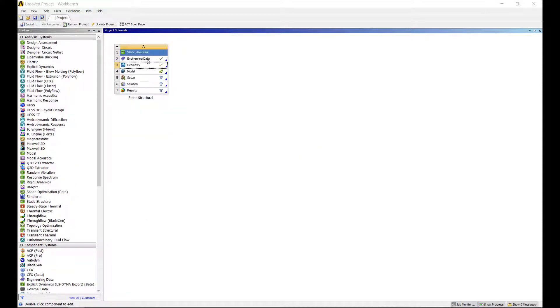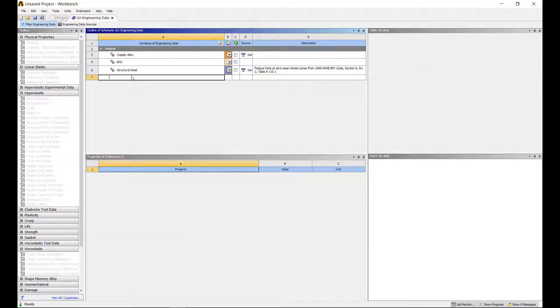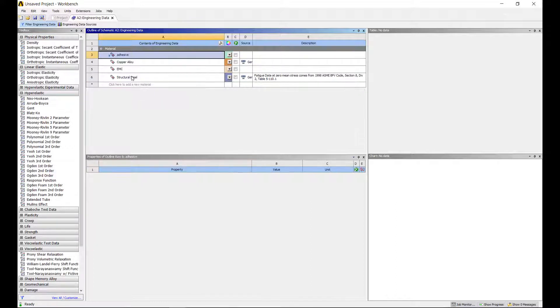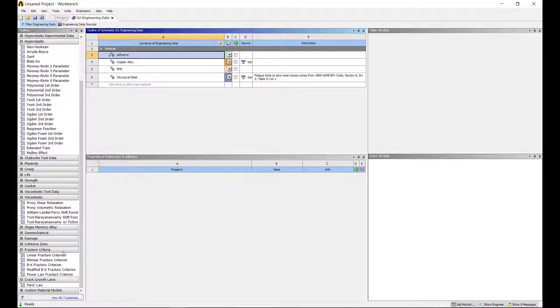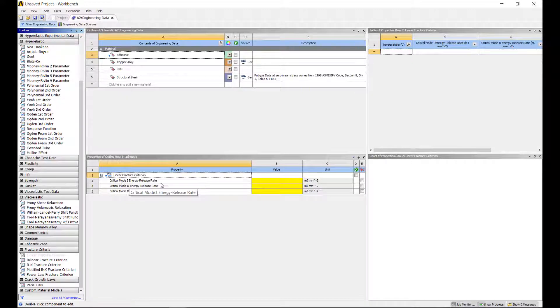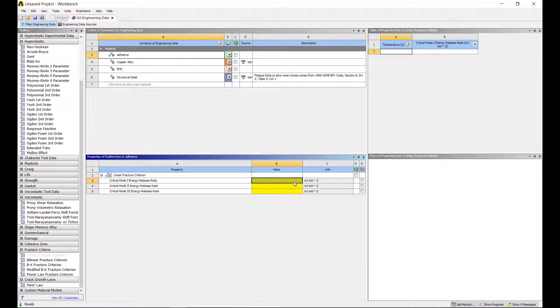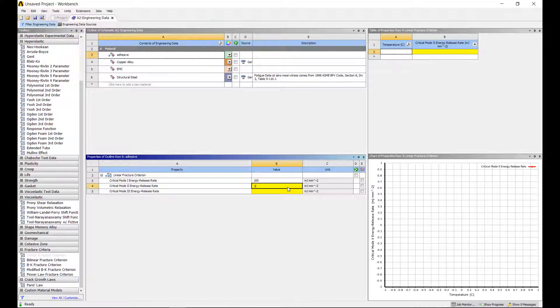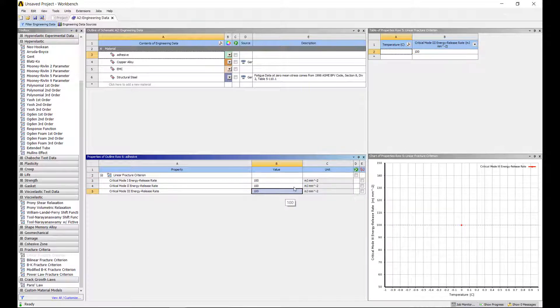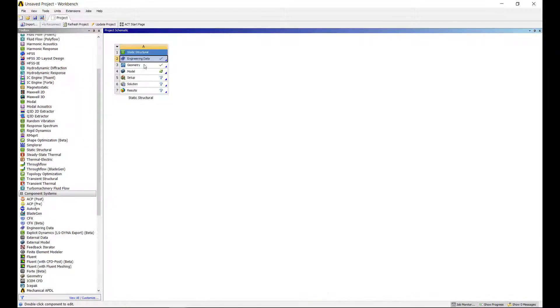The way we do a progressive damage or crack growth simulation is we start by defining the material that will be delaminating or cracking. I'll call it my adhesive. In ANSYS Engineering Data, we can specify different types of Fracture Mechanics criterion. I'm going to go with the basic linear Fracture Mechanics criterion, where we define the critical energy release rate for each of the modes. Based on our test data, we can measure and simulate the critical energy release rate based on things like double cantilever, end-notch bending, or three-point bending testing. I'm going to make up some simple numbers here and demonstrate the process. Certainly, when you do a serious analysis, these values will need to come from experimental correlations.